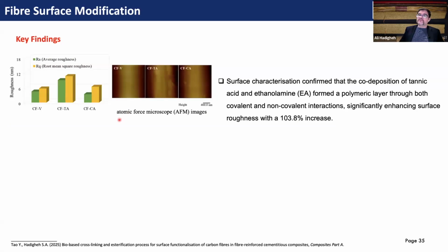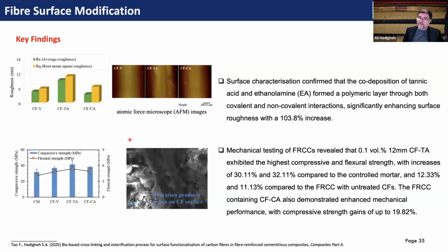And when we look at the AFM images, we see the surface topology of these carbon fibers and the roughness of that. So you see that we are improving the roughness of the surface. We are also incorporating functional groups on the surface. So that increases the bonding between fiber and the cementitious material and improves the ITZ performance. So that's basically very successful, and I think it is quite scalable within the industry and a very simple process that can be achieved with normal facilities that we might have.